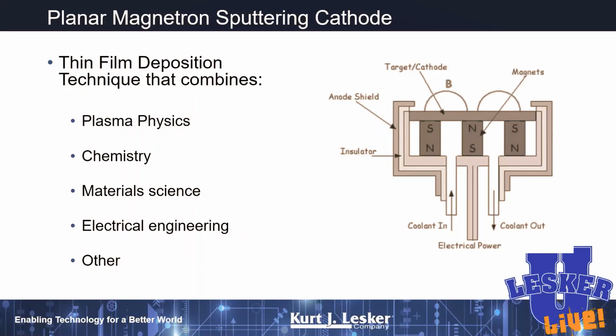And so here's just a cartoon of a sputtering cathode. Here we've got the sputter target, and this is going to be called the cathode part of the target. And then we've got the anode, which is in this case embedded in the thing called the dark space shield. We're actually going to create electrons right in this gap between the anode and the cathode. And the size of that gap is really, really critical. For most cathodes, it's designed to be about 80 thousandths of an inch. Over time, if you've done a lot of aggressive cleaning and things like that, you may have changed the dimensions on that gap, which is going to affect the performance of your gun.